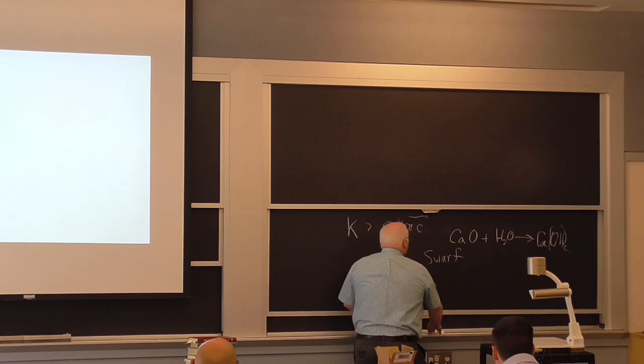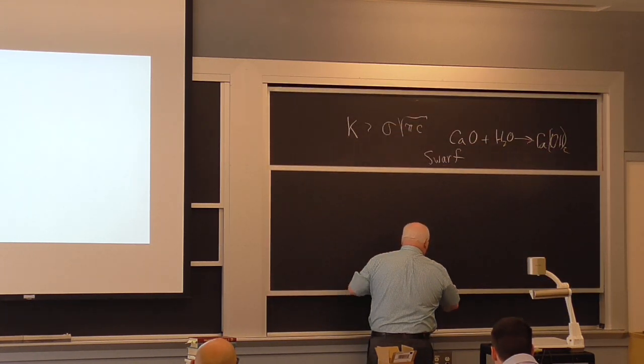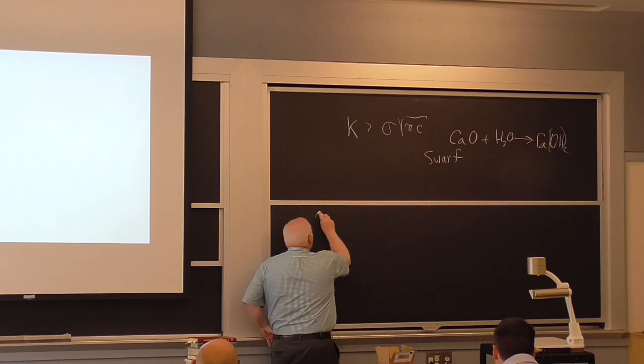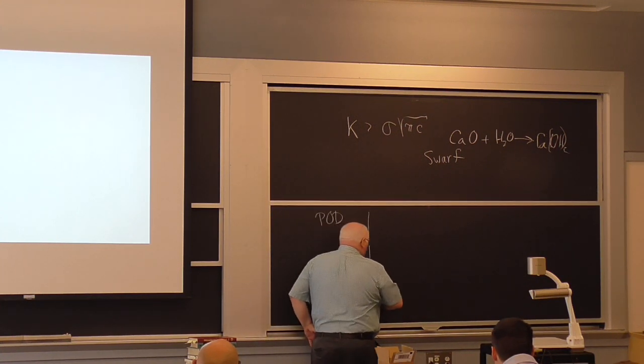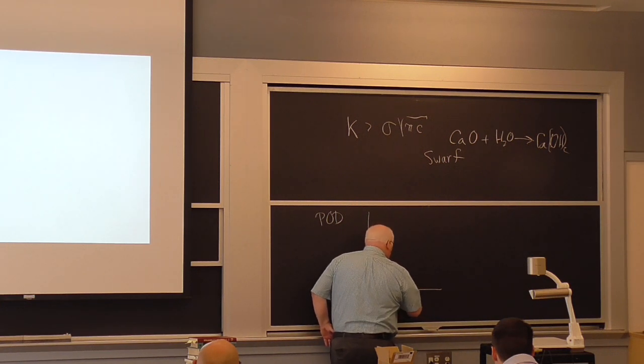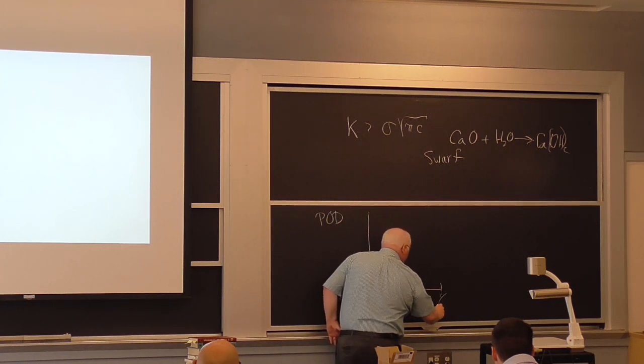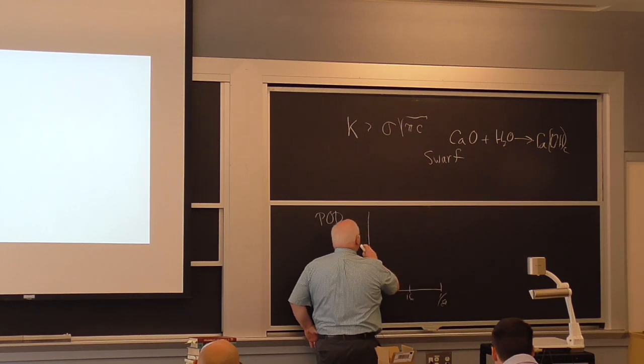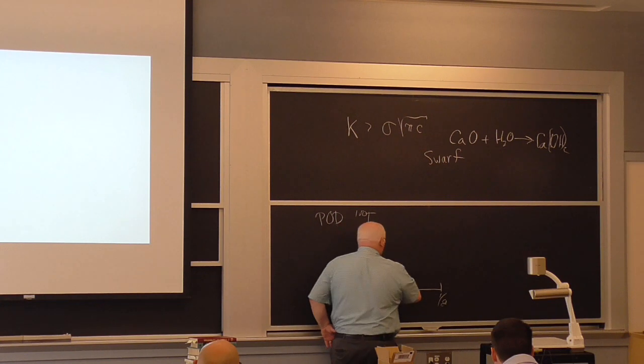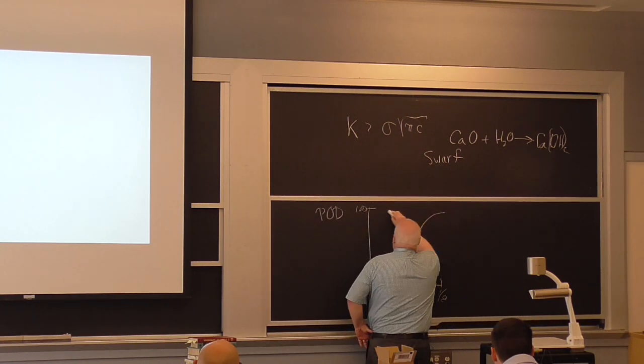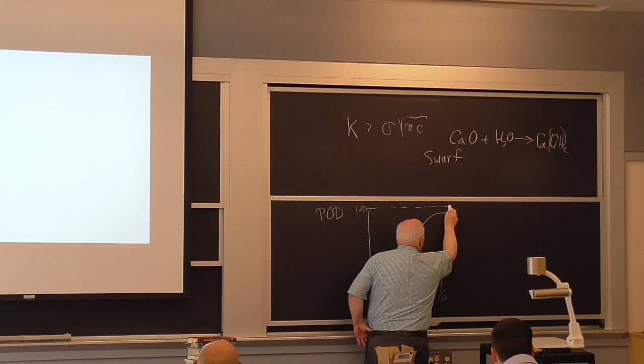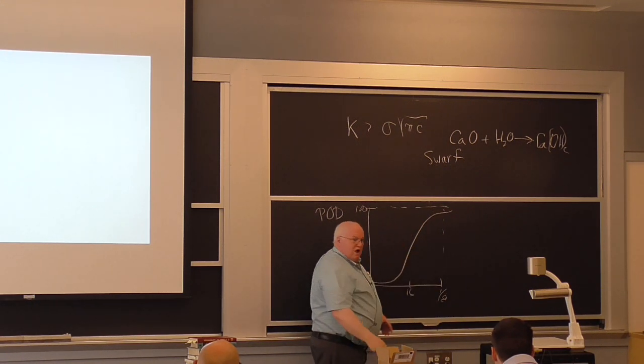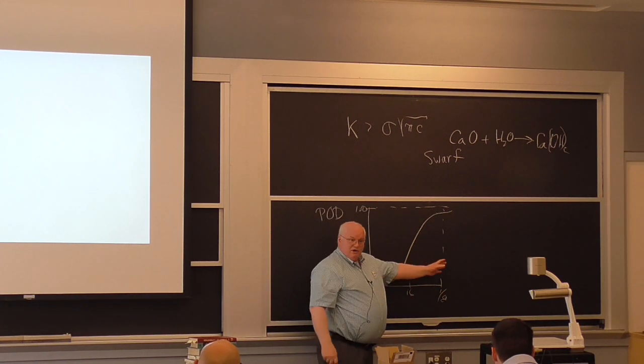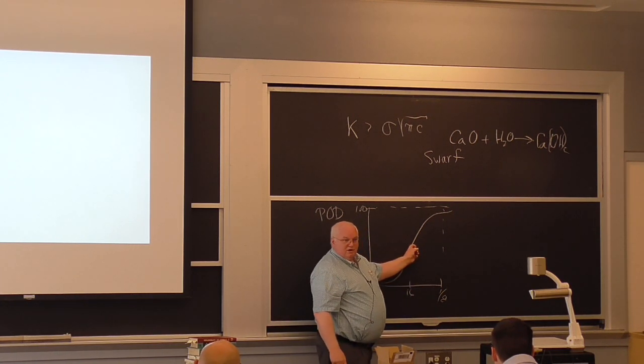Actually, the Air Force did a bunch of studies in the 1980s on what they call probability of detection. And if you plot the probability of detection by flaw size, and I'm plotting this in inches now, because that's what we use in this picture, and this is 100%. You find the curve looks something like this, and you'll be at 95% probability of detection by a manual inspection at 1/8 of an inch. You'll be at about 50% at 1/16 of an inch. These were down here in the millimeter size. Very low probability of detection.